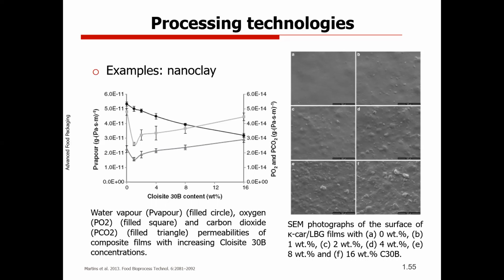On your left, you can see this graph that shows how the permeability to water vapor, oxygen and carbon dioxide change with increasing Cloisite 30B. In the case of water vapor permeability, you have a decrease of the values with increasing concentration of Cloisite 30B, but for oxygen and carbon dioxide, you have an optimized concentration when you are using the lower amount of Cloisite 30B. Then it starts to increase a little bit, but is still lower than the material without any nanoclay. This is explained by the aggregation of nanoclay in the matrix. So nanoclay also needs to be dispersed, and when you increase the concentration of these materials, we are promoting this aggregation, and then the results that we achieve are not as good as expected.